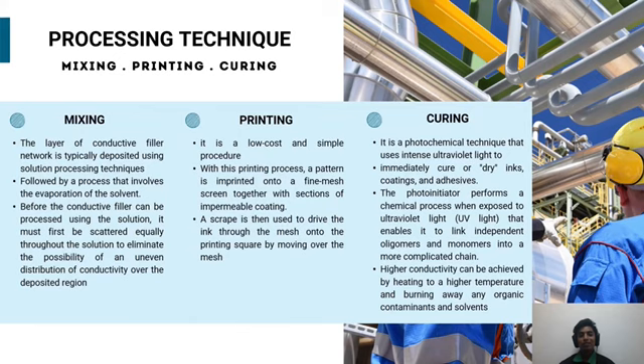It is a photochemical technique that uses intense ultraviolet light to immediately cure or dry inks, coating, and adhesives. The photoinitiator performs a chemical process when exposed to UV light that enables it to link independent oligomers and monomers into a more complicated chain. High conductivity can be achieved by heating to a higher temperature and burning away any organic contaminant and solvent.